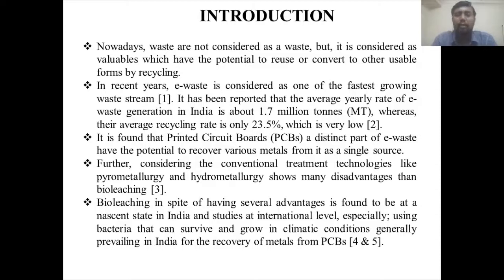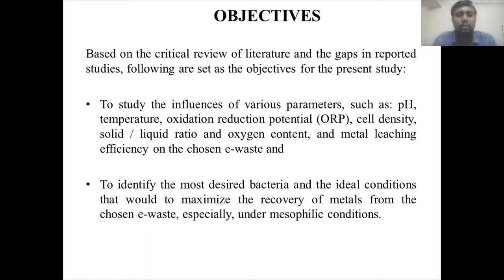So here we have chosen a methodology called bioleaching, other than its counterparts, pyrometallurgy and hydrometallurgy, which have many disadvantages. So we have decided to go for a bioleaching process. We are using a bacteria to recover the metals in the printed circuit boards for proper disposal. The objective of the study is to find the influence of various parameters such as pH, temperature, ORP, cell density, solid liquid ratio, and so on, and to find the most desired bacteria and its ideal condition to recover the metal to the maximum.